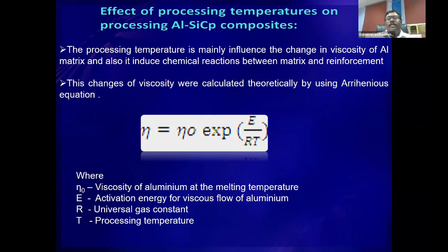So when you have a melt which is kept exactly at the melting temperature and you add reinforcement to it, the reinforcement absorbs the heat. As a result, the melt temperature will be drastically reduced, and the viscosity will be very, very high. So it won't allow the particles to disperse inside the matrix material. Because it is highly viscous, it will never allow the particles to penetrate into the viscous medium, and as a result more agglomerations will be formed. So if you conveniently set the temperature parameter a little high, you will have a lower viscosity, which will be sufficient for the particles to penetrate while the turbulence is created. It will go around and then distribute uniformly.